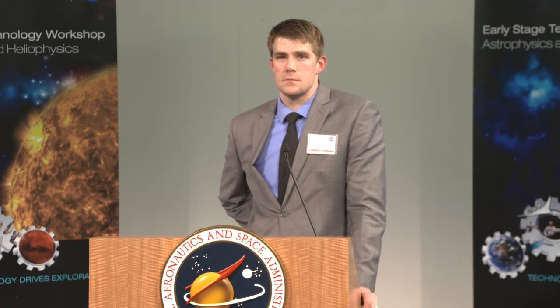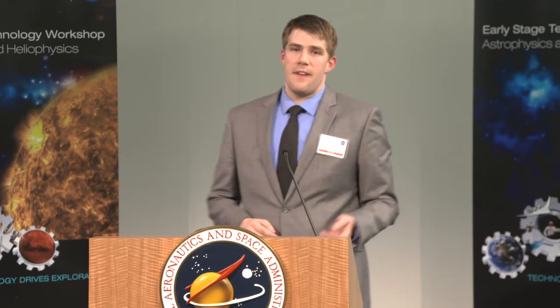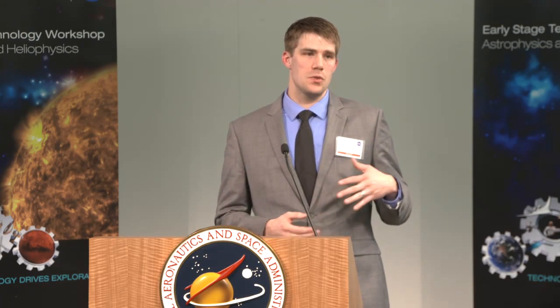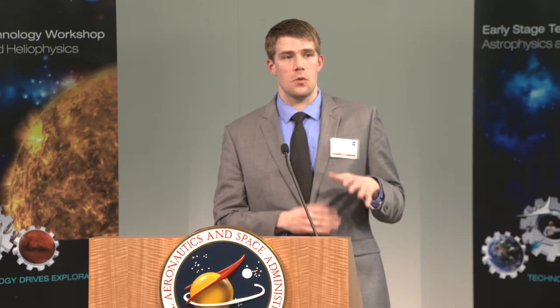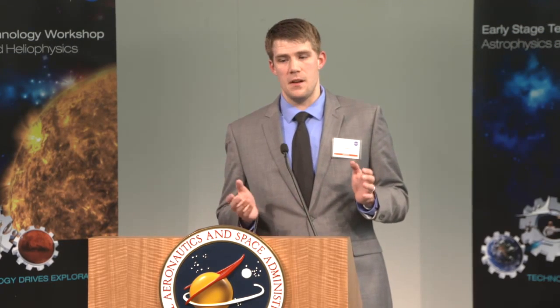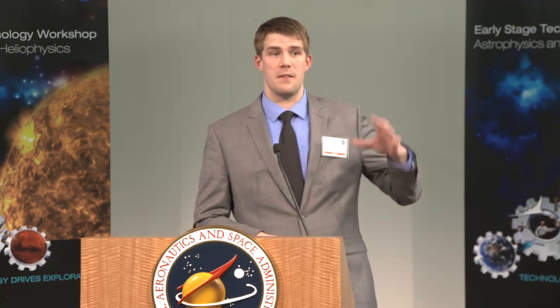Yeah, nice talk, beautiful. You are raising the detection temperature on these. I didn't really catch that. Was that just because of the plasmonic resonance bringing in more signal? It's actually both. That is one of the factors. The data that I showed you at 230 Kelvin actually has no plasmonic structure. That's some older data. That's due to engineering the MBE growth. Quantum dots have a very low density of states, so they have an intrinsically low dark current. If you can provide the right layers surrounding the quantum dots, and you can grow defect-free, the quantum dots are defects, but if you can keep them all at a uniform size and not have any very large quantum dots, that's another key to getting low dark current and high operating temperature.